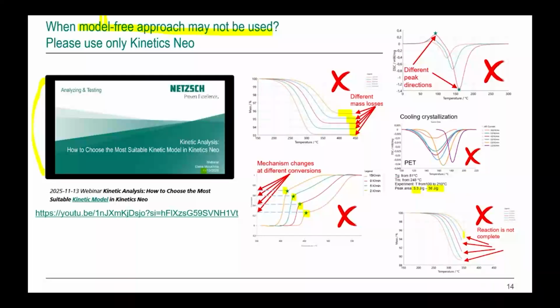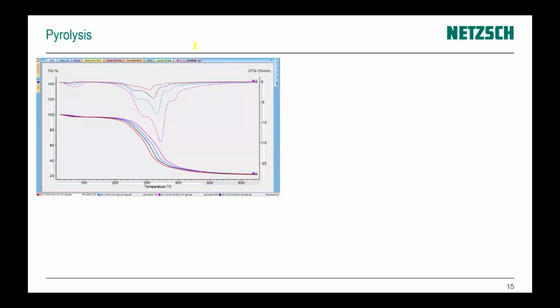Sometimes reaction is not measured up to the end. In this case, we don't know what is the mass loss for 100% of conversion. And again, model-free kinetic doesn't work. In this case, only Kinetics Neo can be used because this is not a basic kinetic evaluation and it could not be used in Kinetics Lite.